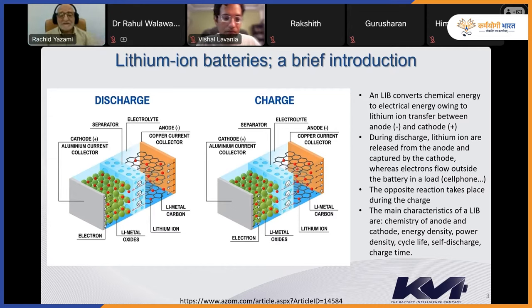So there are three major components in the battery: the cathode, which is an oxide or phosphate; the anode, which is basically graphite or other carbon material, or silicon; and the electrolyte, which is a solution of a lithium salt, mostly lithium hexafluorophosphate, and an organic solvent, mostly carbonates like ethylene carbonate, dimethyl carbonate, and so on.